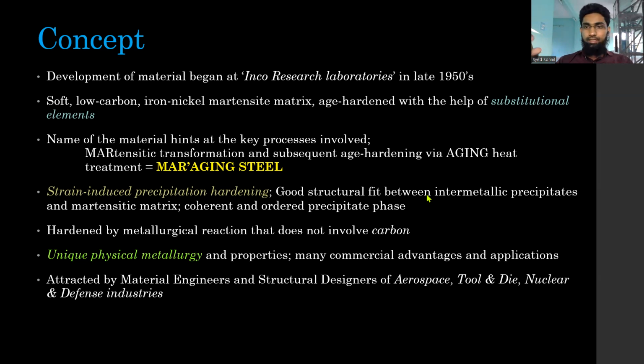So the martensite matrix has a BCC phase, body centered cubic, and the intermetallic phases formed are nano size. To name a few, there are precipitates such as Ni3Mo, Ni3Ti, basically compounds of nickel that we have here. These are intermetallic compounds, and there is even Fe2Mo. All of these, when the material is mechanically loaded, prevent dislocation movement. So the prevention of dislocation is because of these intermetallic compounds which form, and that's what gives the material its hardness and toughness.